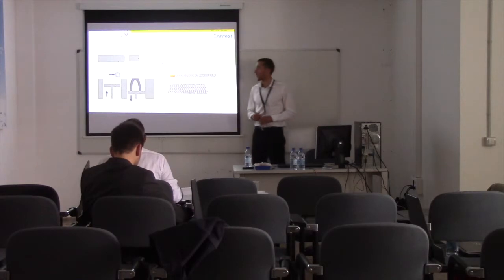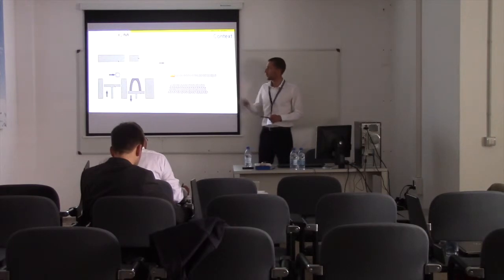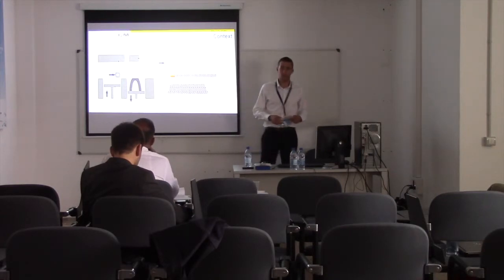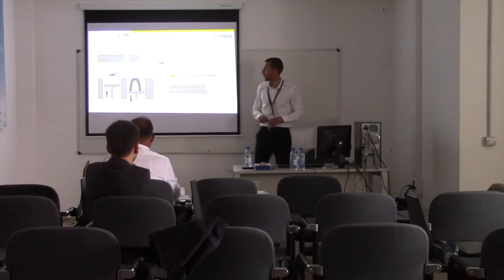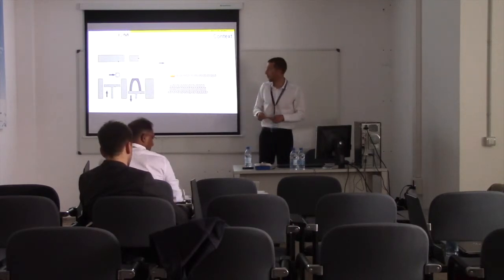There are around 50 parameters that can affect the defect formation in the part, but three main parameters can be dedicated to the quality of the part. It's the laser power, the scan speed, and the scan strategy. However, if we look further into laser matter interaction, with the laser light interacting with the powder bed layer, we can see that the laser beam energy can be set thanks to three parameters.